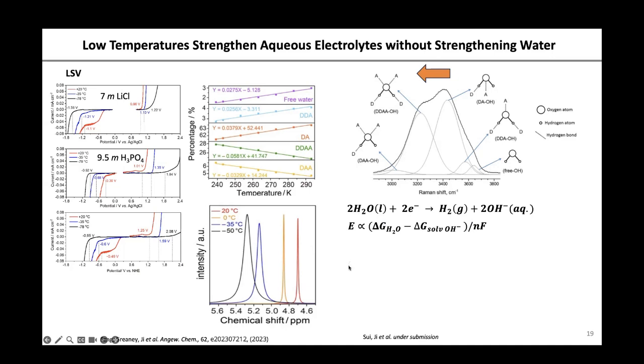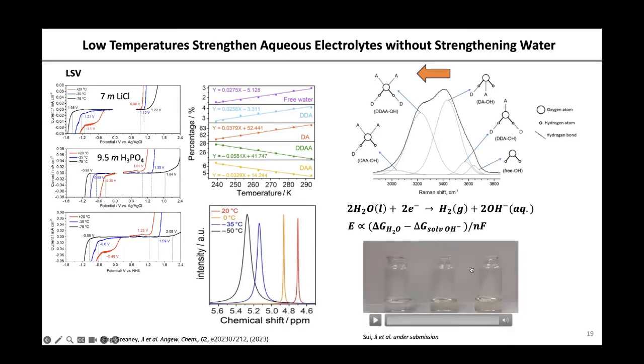It's close to what really happens, but I don't have time to talk about it now for the fundamentals. But I can show you by design of the electrolyte how dramatic the stability can be, right? This is an aqueous solution. What you're going to see is we're going to drop some lithium foil into the aqueous solution, right? This is the most stable aqueous solution we have designed. Look at the lithium foil, quiet, very calm, not exploding at all, right? This is a less stable one. You see some bubbles? This is pure water. That's the electrolyte we designed with the hydroxide solvation heavily frustrated, right? That's going to be something new we will report.